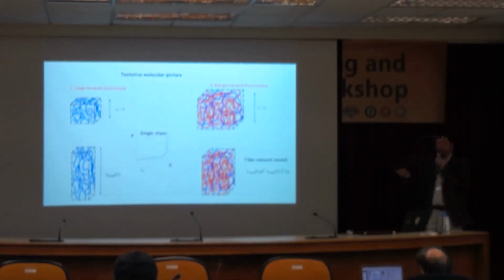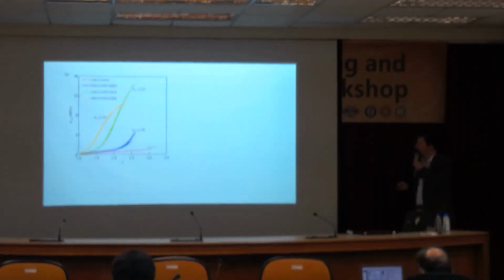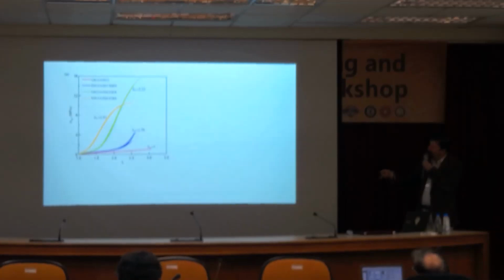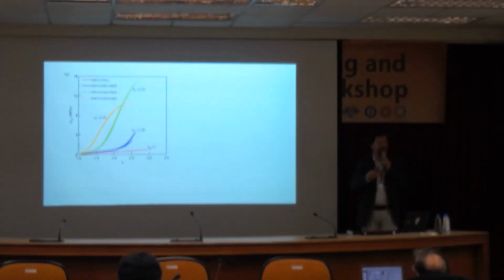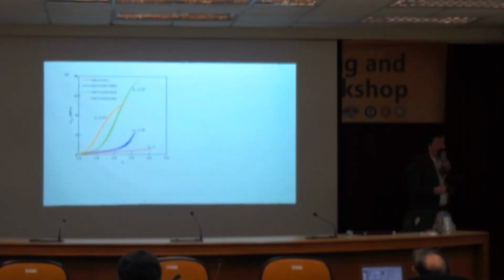If you actually make these materials and you test them mechanically, you stretch them, this is what you get. This is the initial network down here. This is stress versus stretch. This is larger than 1. This is the initial material. This means three times the initial length. This is lambda 0 equal 1, the non-pre-stretched one. As you pre-stretch to 1.5, 2.2, and 2.3, you can see that the stress at break goes up quite a lot. So the material gets much tougher. And if you look at the extensibility, it doesn't change very much.